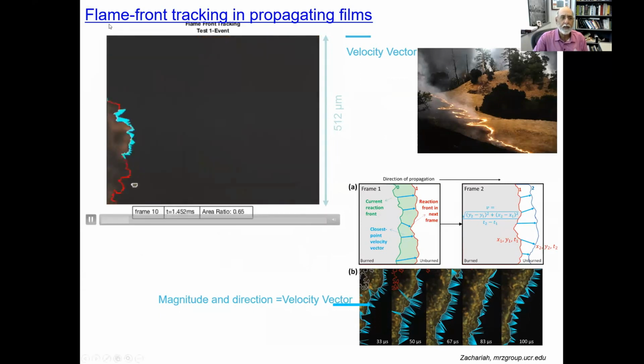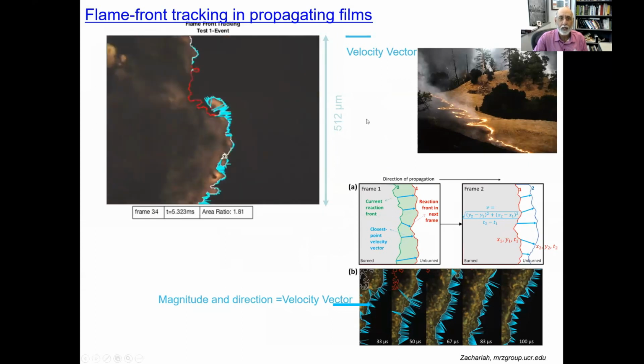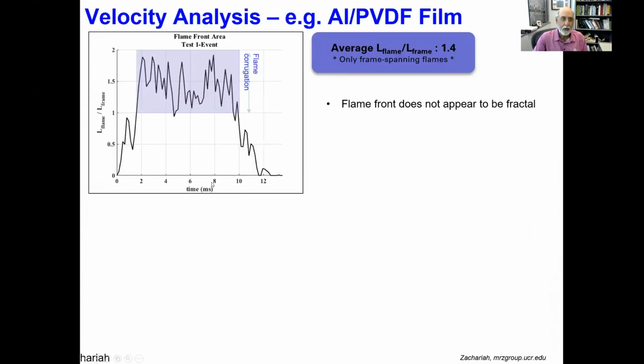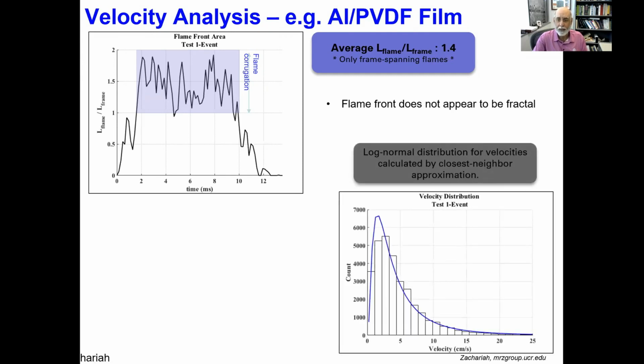This length scale is 500 microns. So it's a small length scale we're looking at. So we can estimate then how big is the flame area relative to the geometric flame area. And this we call the flame corrugation. In other words, in this example, the corrugation factor was 1.4. The flame was stretched out 1.4 times, similar to a turbulent flame where the flame area is stretched out. And that is what gives you the turbulent flame speed enhancement over laminar flame speed.